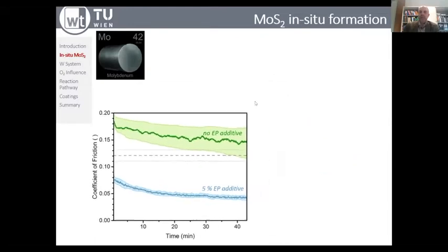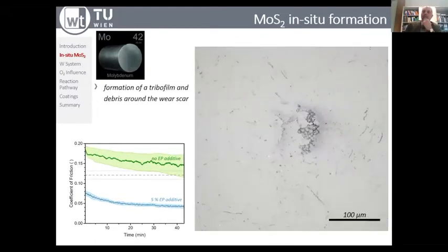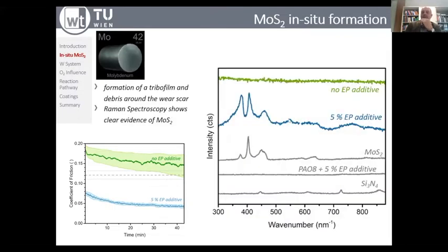A few more comments on the tribofilm itself and the debris around the wear scar. You can see there is a lot of debris around here. We also did XPS, so you can detect the sulfur from the sulfides to some extent. And when you look more closely at this red encircled part with Raman analysis, we took as a comparison the Raman spectra for the silicon nitride and also for the PAO8 with the additives. You see here the characteristic spectrum of MoS2 with the characteristic wave numbers. And you see what happens in case of no EP additive and 5% EP additive. So clearly, also by Raman spectroscopy, you have very pronounced evidence that you actually form MoS2, because the peaks are very much the same as the ones you can find here.